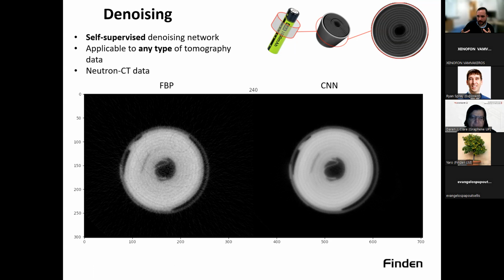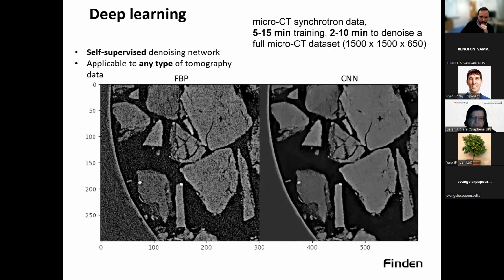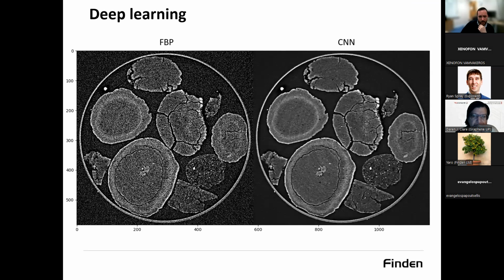So for example, here we're looking at neutron tomography data. Again, we can see the spiral on the right-hand side. The left is very, very noisy. It's even suppressing some of the ring artifacts. Similarly, when it comes to particles, you can see here that we are smoothing them, but without blocking pores. This is also very important. And even here, we have quite a few cracks, and we are not closing the pores. So this is also a very good tool for conventional imaging if you want to do image segmentation.